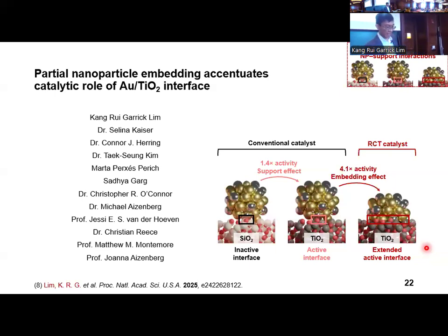Beyond its modular tunability, another unique feature of the RCT method is that it derives catalysts with nanoparticles partially embedded within the support, which not only improves catalytic stability against sintering, but also increases the nanoparticle support interfacial length, which is demarcated by this box. This is in contrast to conventionally prepared catalysts, where nanoparticles are formed or attached onto the surfaces of support materials. In this second half of my talk, I will share how the RCT platform can be employed to disentangle support and embedding effects, and illustrate how nanoparticle embedding can be used as a synthetic tool to accentuate the catalytic roles of this nanoparticle support interface.